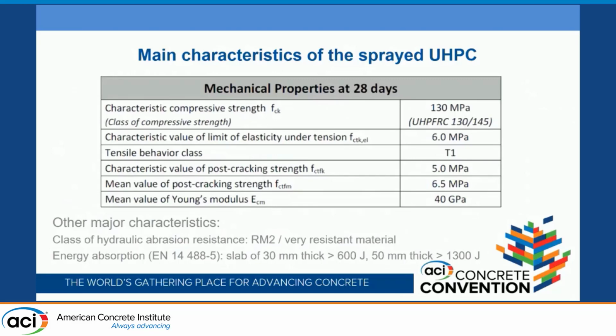Now, let's go into the more technical part of the project. As you can see from this table, the main characteristics of the sprayed UHPC are a compressive strength of 130 MPa, a characteristic value of limit of elasticity under tension of 6 MPa, and a characteristic value of post-cracking strength of 5 MPa. Sprayed UHPC also has a high abrasion resistance capacity. Energy absorption tests were also used to characterize the material. The results are relatively high, with 600 joules for a 30 millimeter slab and 1,300 joules for a 50 millimeter slab.